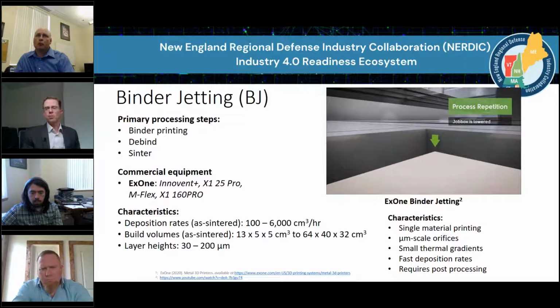things like single material printing. You must have a hole in any sort of solid shell to allow any particles to pass out of your object. That way, because if you bind the outside but have a bunch of powder on the inside, what you're going to end up doing is just fusing those together during the fusion process or the sintering process. But we can get to very high deposition rates, and so you start rivaling some of the, it addresses one of the primary concerns of additive, and that's the slow nature of the process.